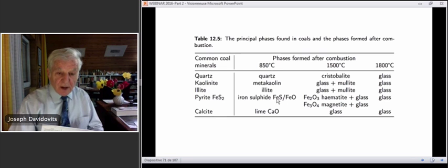Iron sulfide is a very, very dangerous material in our geopolymer system. It is a retarder. And if you have only 1 or 2% of this in a mix, it will never set. Lime, CaO, on the opposite, is a flash set system. So if you take a fly ash that has been manufactured in a fluidized bed, forget about taking it and making a fly ash-based geopolymer cement. You will end up with a poor alkali activated material with no property at all.